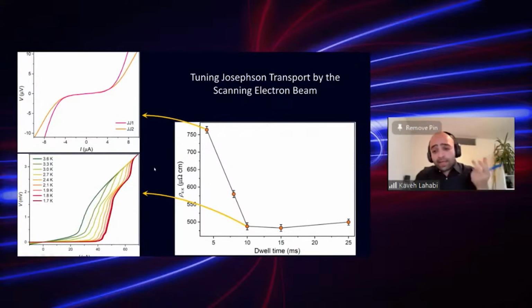So this gave us a way to tune the critical current and also the resistivity of our weak links. And I must say that the junctions are surprisingly reproducible. If I use the same parameters, I always get the same critical current. And this is quite unusual for something that is so disordered and deposited at 10 to the power minus 5 millibars in a microscope.